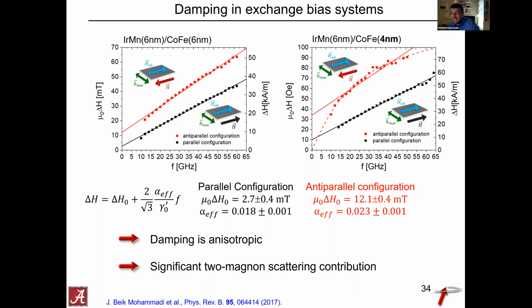Is asking about the spin orbit torque devices. Yeah, so for spin orbit torque switching, the current density that you need to switch, if you lower the damping, you can switch with lower current densities. So when I talk to my students, I always tell them, well, when you measure the damping in a material, it doesn't matter whether the damping comes out to be low or high.